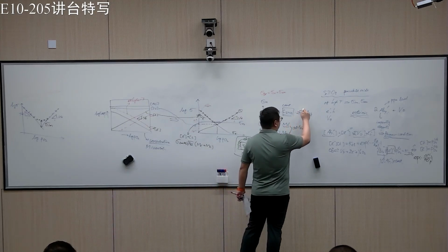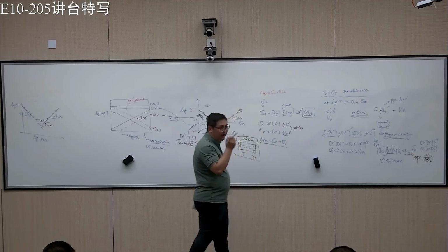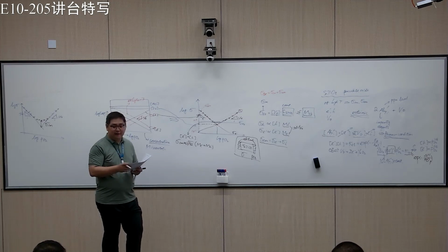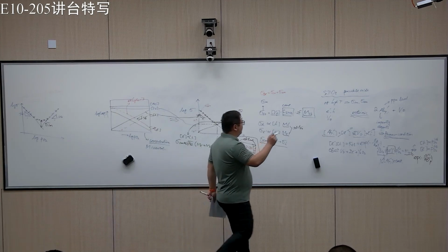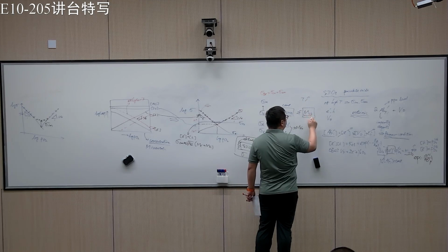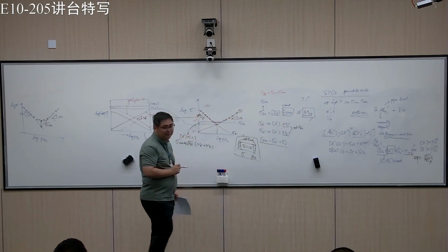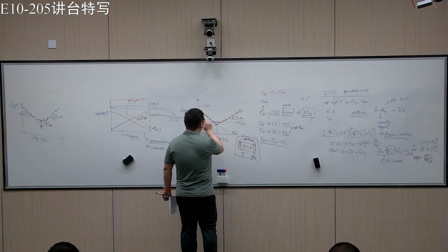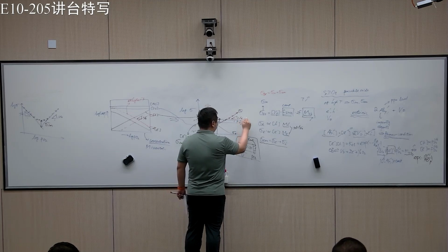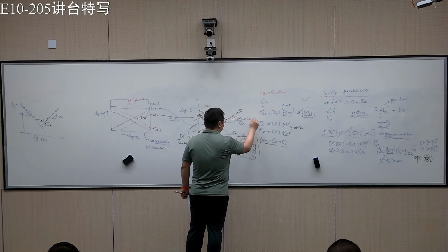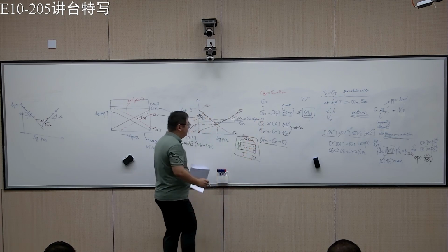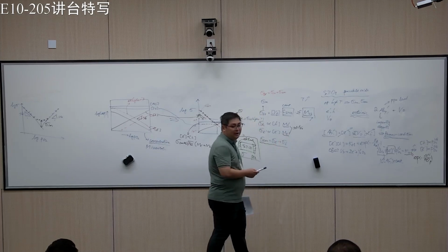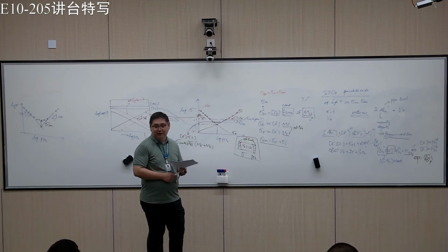First, the temperature is going to affect the mobility of oxygen vacancies. We're going to discuss why that's the case next week. But if you go to high temperature, this thing is going to increase, usually exponentially. So this is higher T. For the electron, if you increase the temperature, the mobility actually drops.